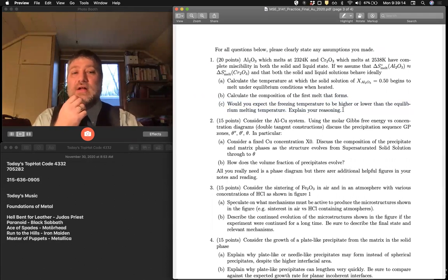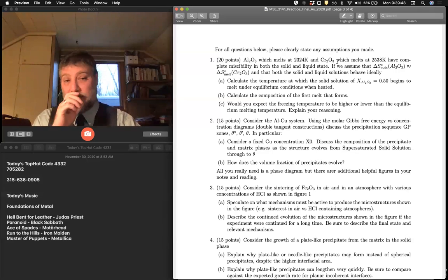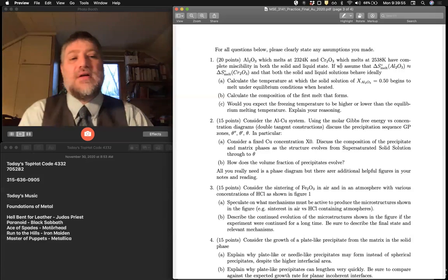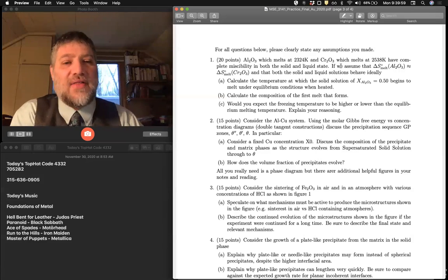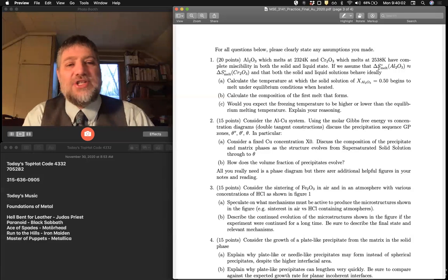Question 1, there is one calculation here, right? Which should be easier than the calculations on the first exam, but it's very much in the same vein. I say we have alumina and chromia, and you have the melting points for each. I also say they have complete miscibility in both the solid and liquid state. And I further say, consider that the entropy of melting is the same for both, right? So what that means is that alumina and chromia have the same crystal structure and equal sizes and all that good stuff, so that the entropy change on melting is very similar.